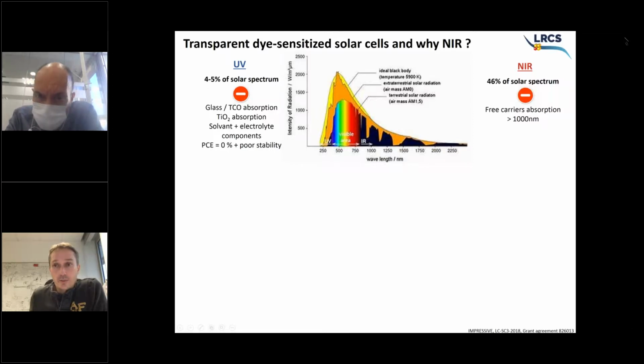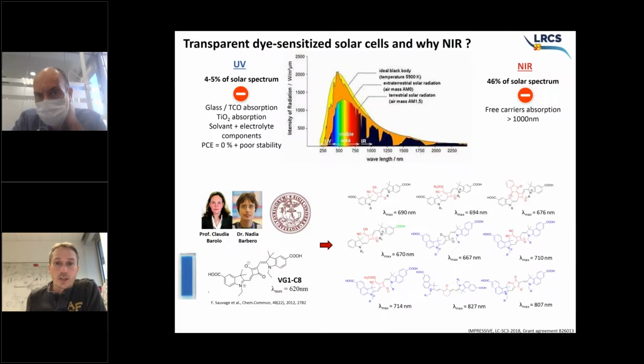So near infrared takes about 46% of the solar spectrum, and the only drawback for a dye solar cell in the near infrared part is that the free carriers in the titania absorb at about 1000 nanometers and above, which will reduce part of the transmitting light in this region. So the open window there is around 750 to 1000 nanometers, I would say, for dye solar cells.